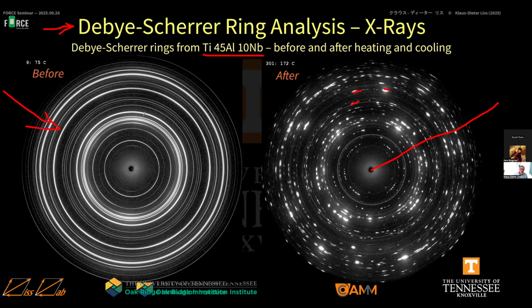Now we can go into detail already here. You see here's more intensity and here's more intensity and there's more intensity. And if you draw that up, you get a reciprocal lattice, and this reciprocal lattice is texture. Yeah, this also belongs here and something here. So you see that there are orientations or correlations between the different rings, and these correlations between the different rings are orientation correlations. So it's a Blackburn orientation correlation in that material upon a phase transformation, or the Burgers or Potter orientation correlations. So all that we can read from just the static images here.